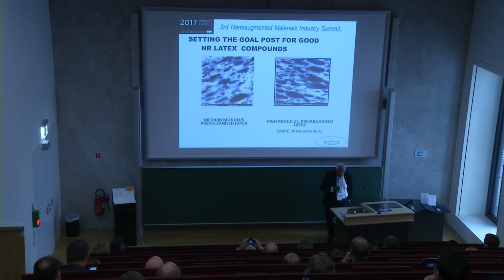This is some 10 photographs that we took at our research center in the UK called Tun Abdul Razak Research Center, and this is the latex which has been already vulcanized. That is, we have different grades of latex with different levels of tensile and modulus properties and other physical characteristics. So here you will see that there are two types. The one on the left is what we call a medium modulus latex, and this is a high modulus latex. Now, a medium modulus latex goes into applications such as gloves and balloons. Actually, a low modulus goes into balloons.